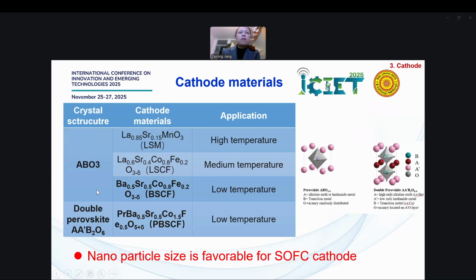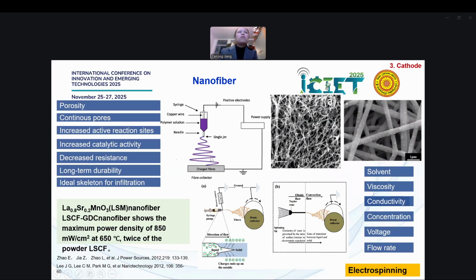So sometimes it's good to get a good cathode, but sometimes it's a risk for a long-term condition. So we chose lanthanum strontium cobalt iron as a cathode, to see if we can prepare some nanofiber. We use this electrospinning machine to spin our solution onto this collector. After that, we got some porous nanofiber, with a lot of continuous pores, and it's a good thing.